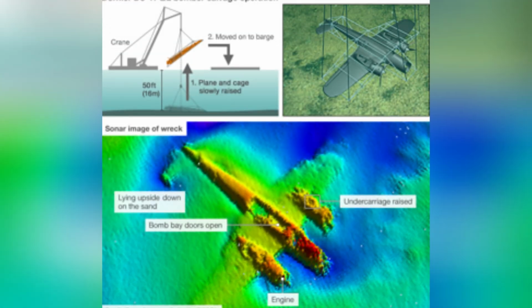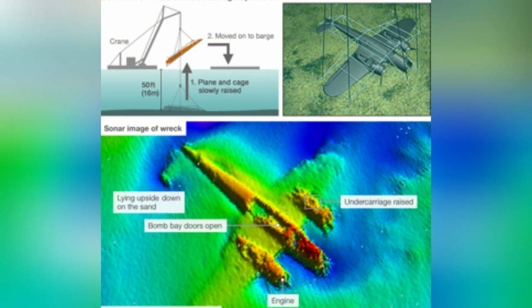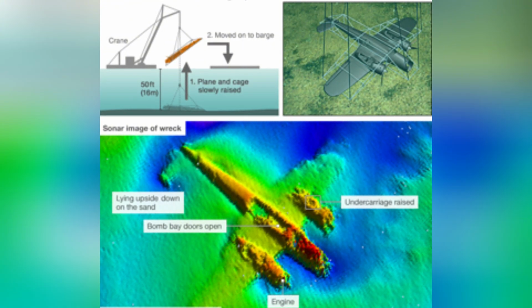Over 7 decades, the protective sediment of the Goodwin Sands had shifted. This process, known as tidal scour, occurs when the velocity of water increases as it flows around a seabed obstacle, eroding the sand directly adjacent to the object. The scouring action had exposed the aluminum skin to oxygenated seawater. The chloride ions in the water had begun to penetrate the grain boundaries of the metal, causing the material to exfoliate. The layers of the alloy were separating like damp paper.